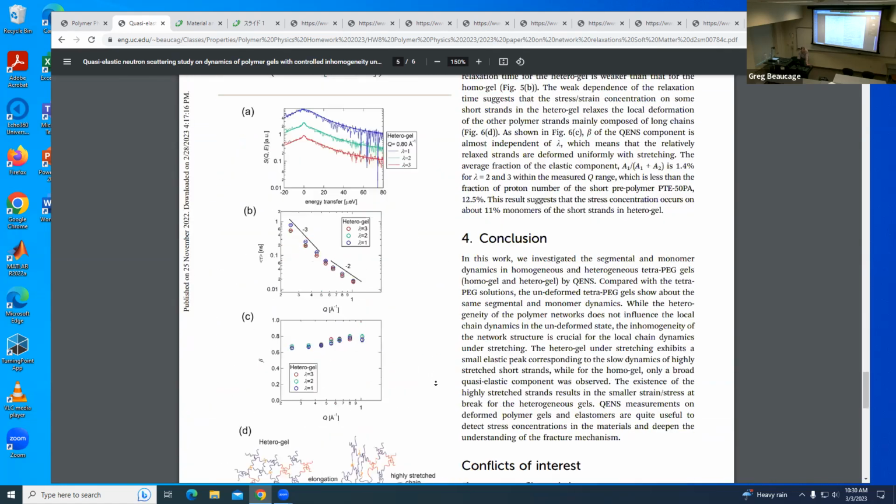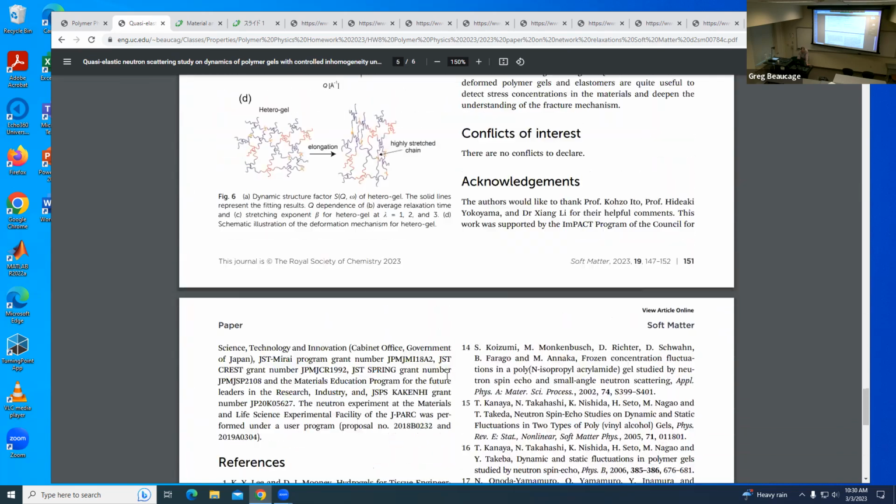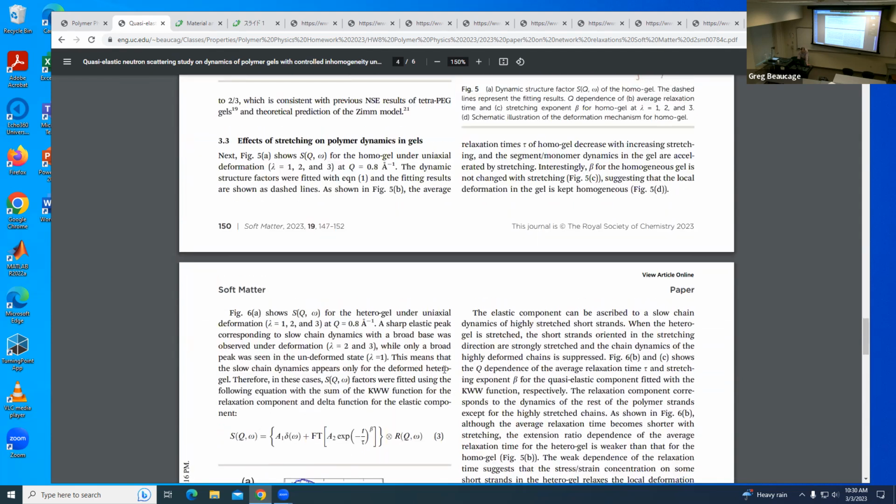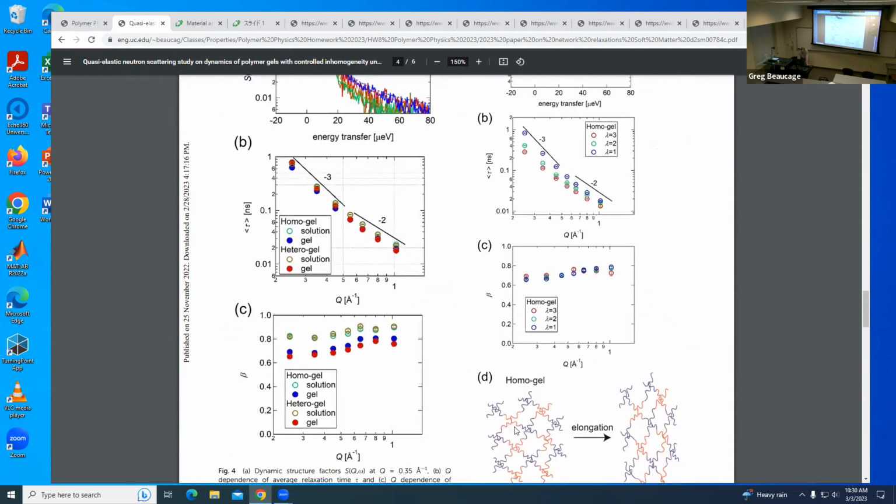I think that there's a lot of problems with this paper, though. First off, stress relaxation is a huge problem. Second of all, the reactions aren't perfect, right? So normally if you're going to do model gels, you would take the gel, make it, and then de-swell it, and then swell it in the solvent again, like water, so you can wash it to get rid of the chains that didn't react. Then you'd measure the modulus so you can get the cross-link density. So you could project what the cross-link density should be in your mind and what it actually is. And that means there's a lot of dangling ends in it.